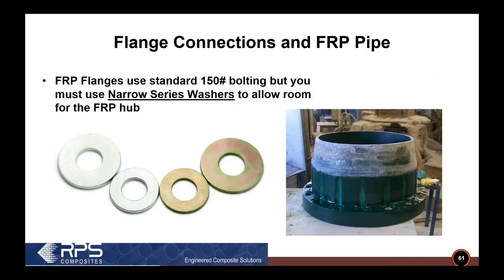And when it comes to washers, the key really is to just use a narrow series washer. You can see here in this picture, the flange on the right hand side looks like it's scalloped out. It's actually scalloped out because you can imagine the flange thickness needs to come up onto the hub of the flange in order to make the flange stiff enough. And that interferes with your standard ANSI drilling patterns. So in this case, we've actually spot faced it for a narrow series washer. You can see if I used a regular wide washer, it would cut deeply into the fiberglass, which would not be a good thing.